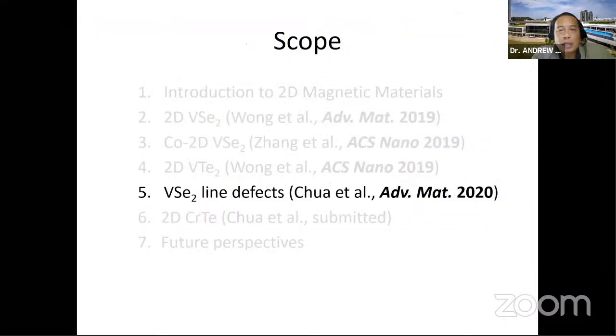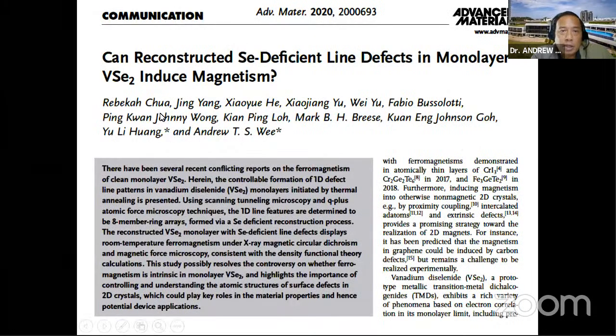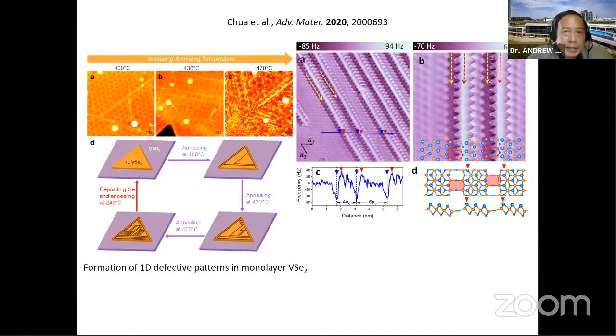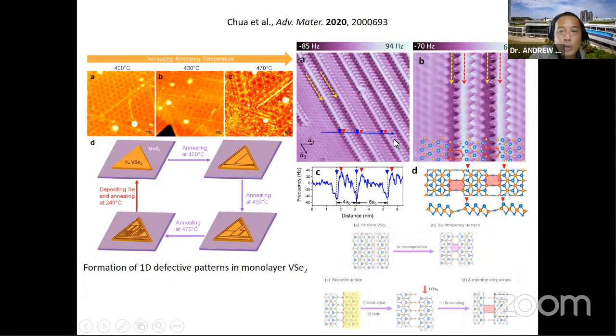So we wanted to do this work carefully in our STM using MBE-grown samples. Our PhD student, Rebecca, who just submitted her thesis, basically asked the question: can selenium-deficient line defects in monolayer vanadium diselenide induce magnetism? So she deliberately heated the sample to cause an increase in the line defects that you see. And these are STM images of the line defects, which we can see are due to selenium deficiencies.